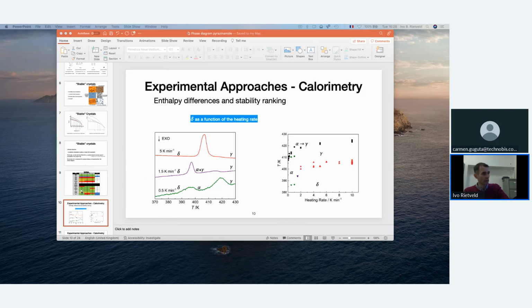And it just keeps on going down, and at a certain point, the DSC just cannot go any slower because you don't see any peaks anymore. So what we did was we put different samples into an oven at given temperatures. And obviously, here we go off alpha, but we also had gamma samples at these temperatures. But this is just to show the final result that all alphas above a certain temperature turned into gamma. Then we, at a certain point, saw a mixture appearing where just a little bit of gamma was formed. And at the opposite side, so to say, where the gammas were put into the sample, we could see alpha form at a given point.